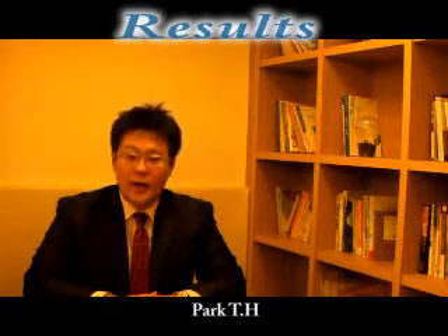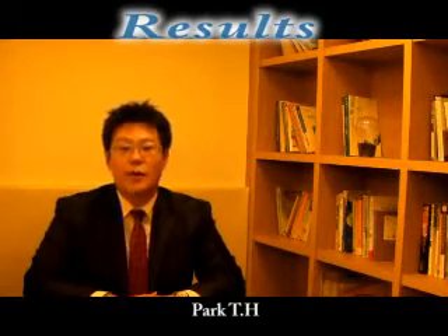This part is the conclusion of our study. As a result of the cross-section of the specimen, it was examined that filler dispersed without concentration, and the 5.08% specimen had excellent dispersibility. From XRD, the characteristic of each specimen showed slight peaks because of the contribution of typical amorphous polymer, broad peaks between 14 and 25 degrees. So I'll show the electric breakdown strength like this.